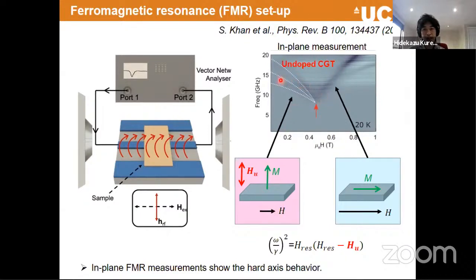So the shape of the peak looks like this arch-like dip shape. That's because this is the hard axis behavior. On the left-hand side, when we apply the magnetic field, we try to reduce this internal out-of-plane uniaxial anisotropy field as you increase the magnetic field, so that the spin wave energy goes down as you increase the magnetic field. But once fully polarized, this is an almost polarized regime, now M and H are in the same direction. Then you can just increase the spin wave energy by increasing the magnetic field. So that's the typical picture or behavior of a hard axis behavior. Please just bear this in mind.